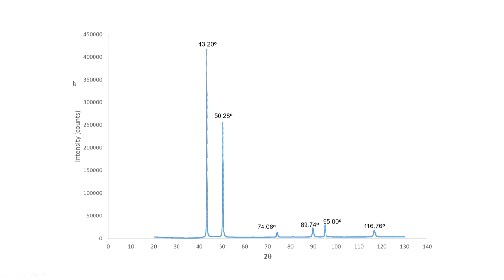So, if you write down the Bragg equation, and this is specifically for cubic crystals that I am talking about, as d reduces, for Bragg's law to be satisfied, sin theta must increase. So, the first peak, which is this one out here, would have the largest d value. The reflection would occur from those sets of planes which have the largest d value, and of course, there is no extinction for those sets of planes.